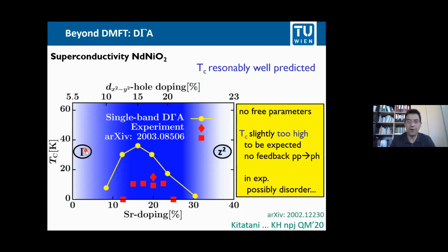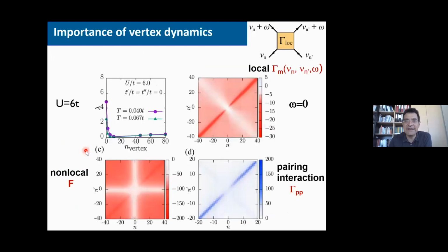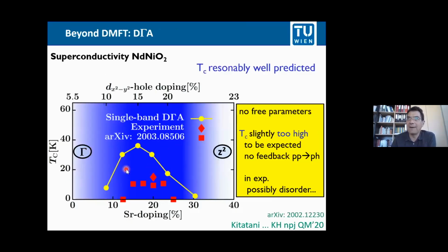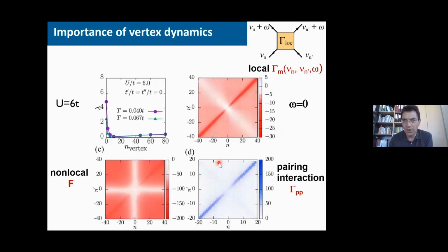Okay, so that was quite exciting. We have calculated TC. Let me just explain to you why the TC is rather low. So if you do a RPA calculation and many other calculations, you would end up with TCs that is not 40 Kelvin, but 500 or 1000 Kelvin, way too high. And the reason for that is the vertex dynamics, which we take properly into account in D gamma A. So our starting point is a local vertex with a full frequency dependence taken into account.